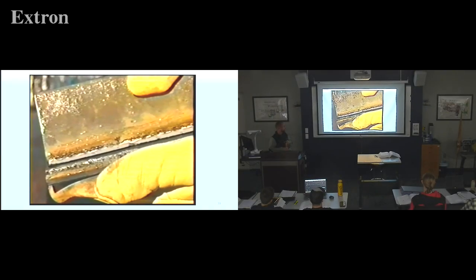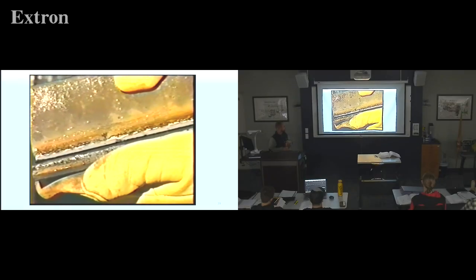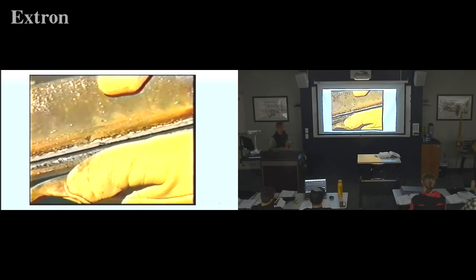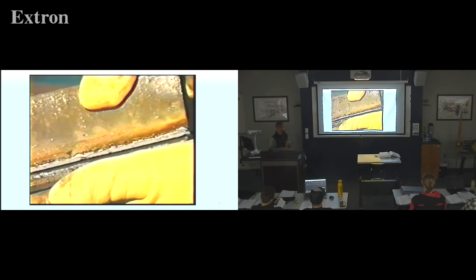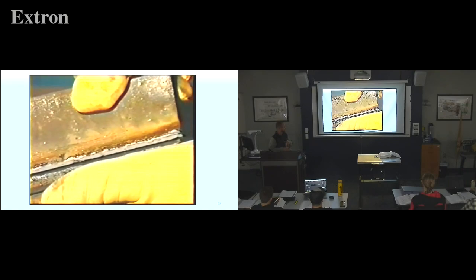The fractured surface of the weld shall show fusion to the root of the joint and shall exhibit no incomplete fusion to the base metal, and there shall be no inclusions or porosity larger than 3/32 of an inch in greatest dimension.